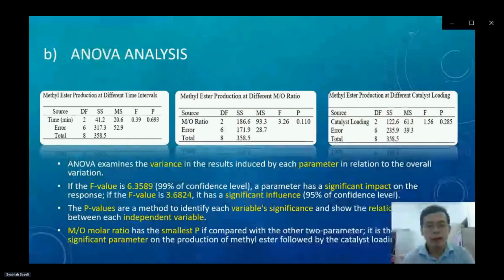Then the next optimization study is the Anova analysis. Anova is used to examine the variance in the result induced by each parameter in relation to the overall variations. If the F value is 6.3589, the parameter has a significant impact on the response. If the F value is 3.6824, it has a significant influence. The P values are a method to identify each variable's significance and show the relations between each independent variable. From the study, MO molar ratio has the smallest P compared with the other two parameters. So it shows that it is the most significant parameter on the production of methyl ester, followed by the catalyst loading.